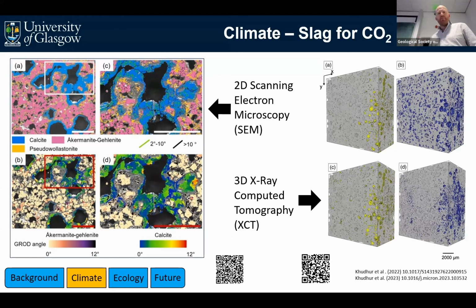And we can see in the two panels A and C on the top left of this slide, we've got a kind of pink color. That's our fresh slag minerals. The blue color is the calcite that's mineralized, that's CO2 from the atmosphere. And there's a bit less, but a sort of yellowish zone in between. That's a different mineral called pseudowollastonite, which essentially is formed when that calcium has been leached out of the slag.